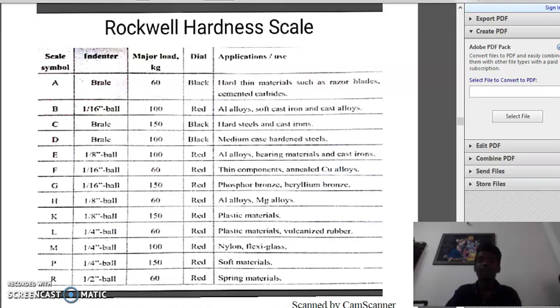Another indenter is Brale of scale symbol D. Its major load is 100, the dial is black, and it is used for medium case depth. Its applications are medium case hardened steels. And an indenter of 1/8 ball has scale symbol E. Major load is 100 kgs, and its dial is red. Its applications are aluminum alloys, bearing materials, and cast irons. Another indenter is 1/16 ball of scale symbol F. Its major load is 60. Its dial is red, and its applications are thin components and annealed copper alloys.